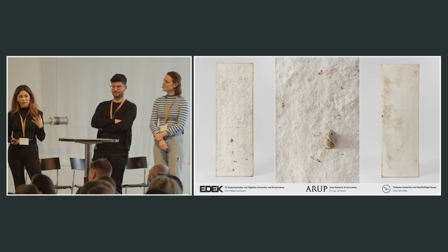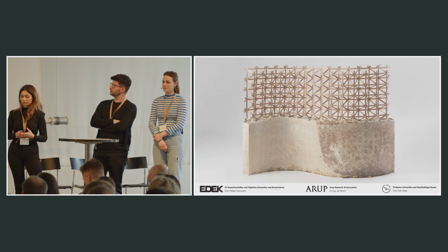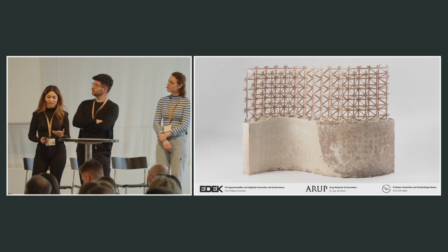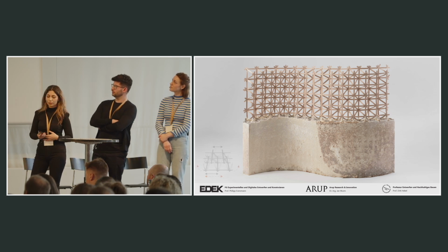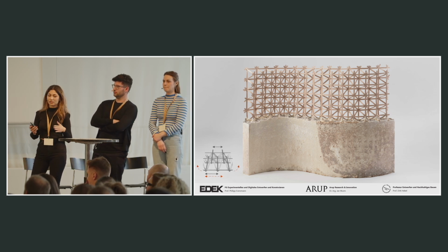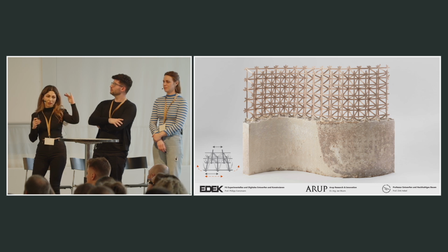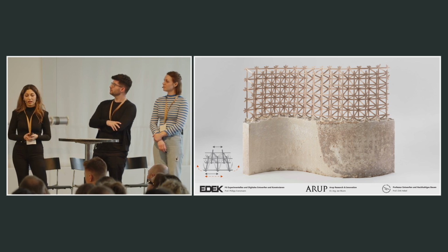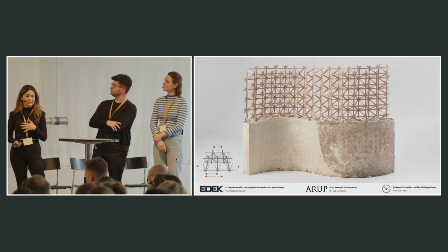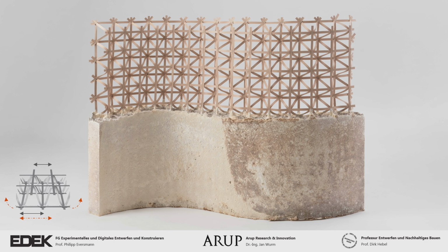We then wanted to see the design possibilities this lattice offers and produced a curved lattice. This single curved prototype was achieved by varying the distances between the veneer strips on the top and the bottom of the lattice. And to do that, we first designed the target geometry, and then we unrolled the lattice strips and welded them together to reach the desired curvature.